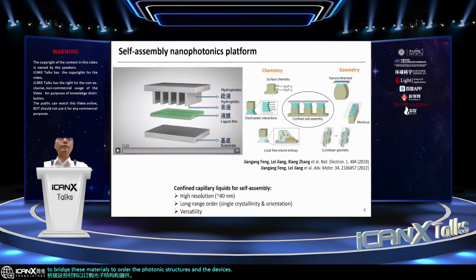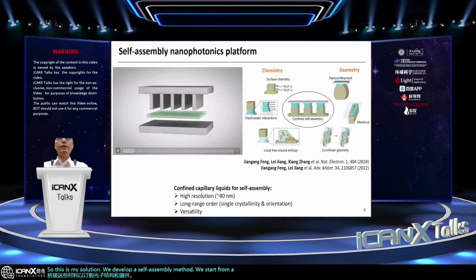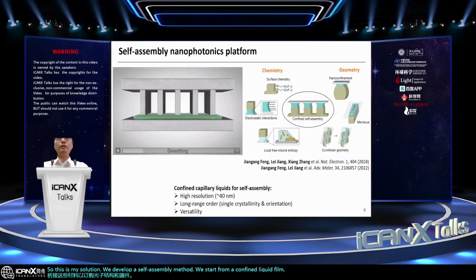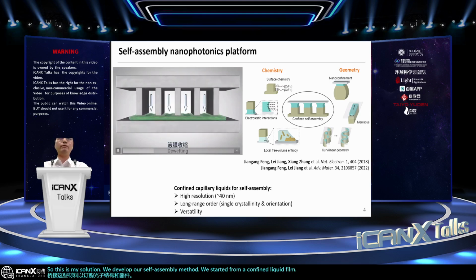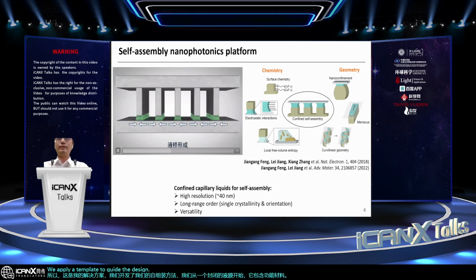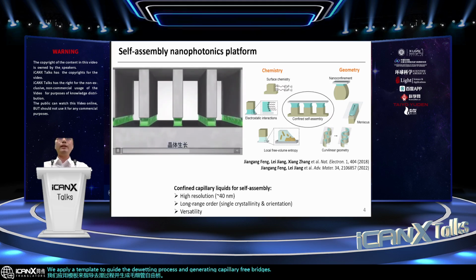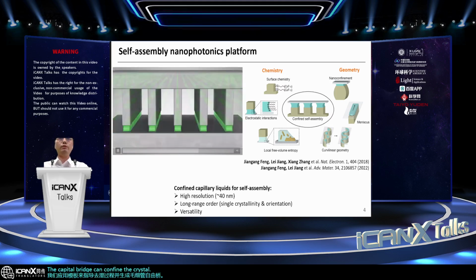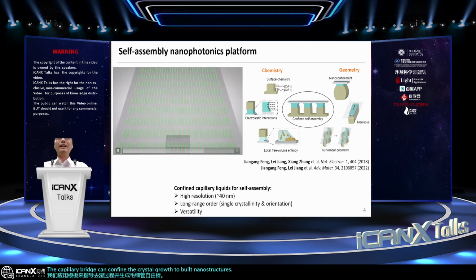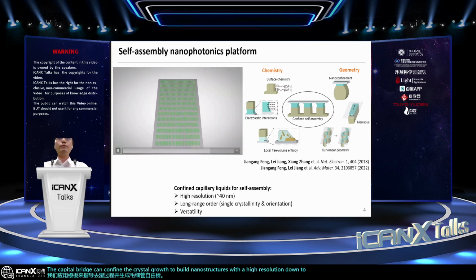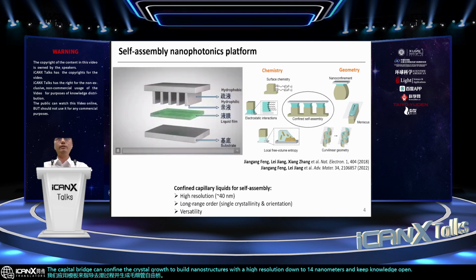So this is my solution. We develop a self-assembly method. We start from a confined liquid film, which contains functional materials. We apply a template to guide the dewetting process and generate capillary bridges. The capillary bridge can confine the crystal growth to build nanostructures with a high resolution down to 40 nanometers and keep long-range order of materials.